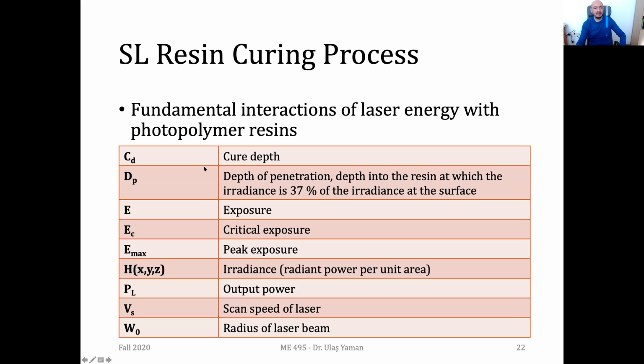And for the modeling part, we need to have some variables, and these are the variables. The first one is the curing depth, and then we have depth of penetration. This is a variable obtained by calculating 37% of the irradiance at the surface. So you need to know the irradiance at the surface. Once you know it, you can simply multiply it with 0.37 to obtain the depth of penetration. And then we will have some parameters about the energy, which is exposure. This is the energy we apply on the material, and we call it exposure. We also have critical exposure, which means that if you apply this amount of energy on the material, then it will be solidified. That's why we call it critical exposure.